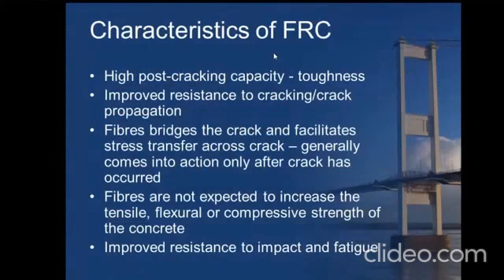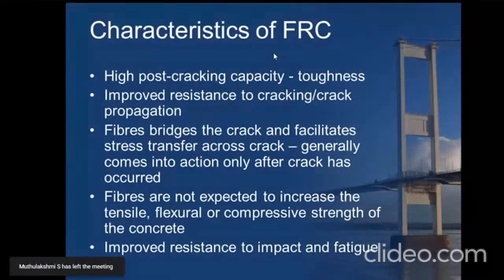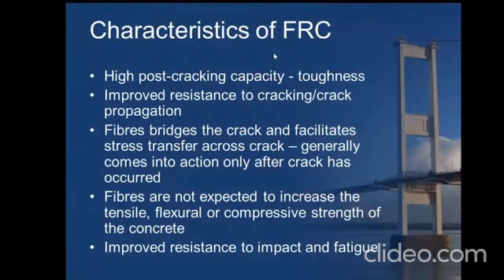So the characteristics of fiber reinforced concrete: generally it improves the flexural toughness of the material, and it has been used very successfully in bridges, and nowadays, as I told you, in pavements. Many concrete road pavements have started using this fiber reinforced concrete. They have started using basalt fibers, because when we are using steel fibers, as the concrete erodes, your steel fibers will be popping out, damaging the tires.